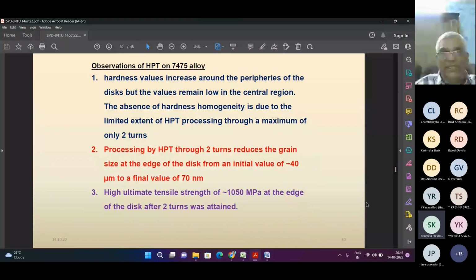it is high. The absence of hardness homogeneity is due to the limited extent of HPT processing through a maximum of 2 turns. So we have done only 2 turns here, and we wanted to see how HPT is useful for making strength. We can see that we have reached 1050 MPa. Processing by HPT through 2 turns reduces the grain size at the edge of the disc from an initial value of 40 microns. As we have seen in earlier images, whether you take optical microscope or SEM images, when you have taken the as cast material, it is almost 40 microns. And after HPT of 2 turns, the average grain size has come to 70 nanometers. And not only getting such a very small grain size of 70 nanometers, we have got an ultimate tensile strength of 1050 MPa at the edge after 2 turns.